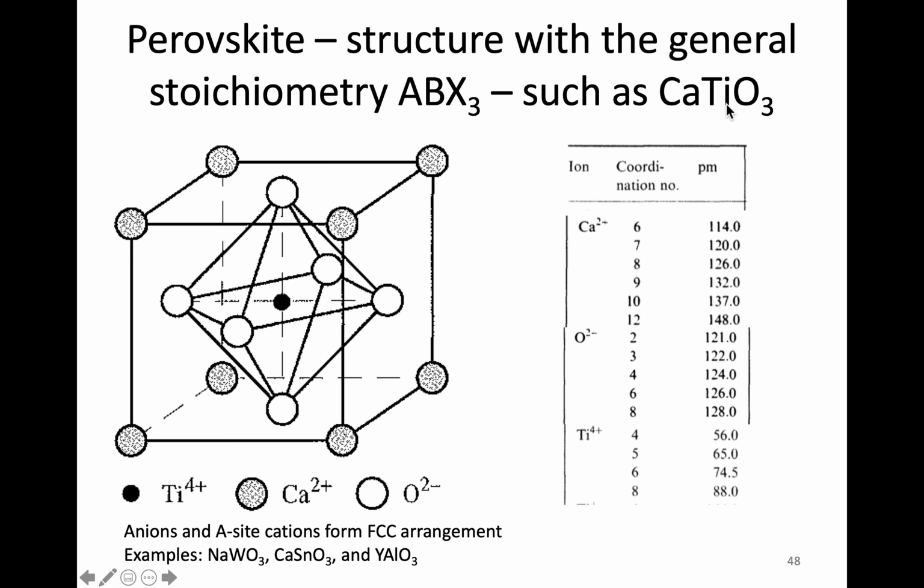The other, calcium and titanium, you see that the black one is inside the unit cell, so that is 1. And then if they're on the corners of a cube, they count as 1/8, so there's 1 atom there. And so the main thing you have to do with that is determine the relative size. You can kind of see that these are larger, whereas this one's smaller. You can also work out the charge balance of this. If we know oxygen is 2 minus, then you have to have a combination of +6. Calcium tends to be 2 plus, and so titanium, that leaves 4 plus.